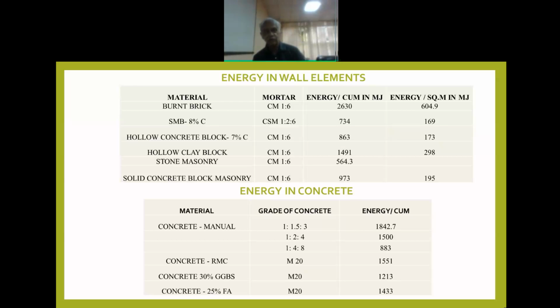Hollow concrete block is also a good option, and it has slightly more energy, 863, still very much less than brick masonry. Hollow clay block is about half the energy of the brick masonry. Even that is better than brick masonry. Advantage is hollow clay block is there. The density is very low, often around 1000 kilograms per cubic meter. And because of reduced weight, you can build higher stories.